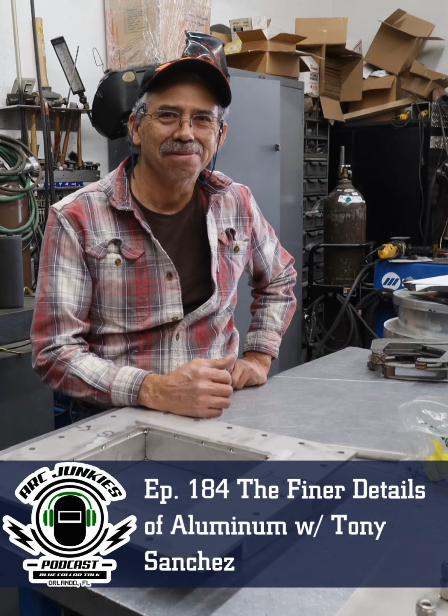Well, that's why I say you got to watch for them monkeys, because them are them pinholes that are going to be on that startup and in places, especially when you got 2 different thicknesses of metals. A lot of them pinholes will want to go to that thicker side all the time. So once I get to that point, then with aluminum, I push a concaved puddle. That's how I learned to do aluminum very well. Instead of having a convex puddle right under you, you push it till it's concaved. Then that's the way you know you have enough heat in that material.